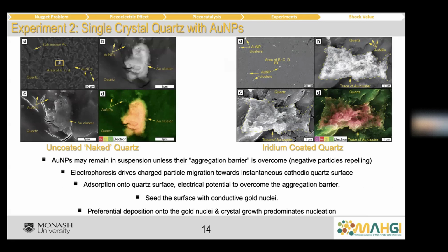I like the results here. They're pretty nice. You can see these bright spots on that image. Those are individual clusters. So we're growing things that were a couple of microns across from solutions that started with 2 nanometer, 20 nanometer particles. Usually when people coat things with nanoparticles, they tend to grow crystals instead of having an even coating. It's sort of common that that's the result.